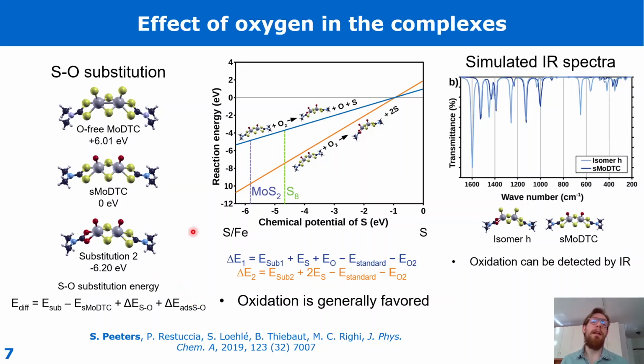To better generalize this result, we built a stability diagram in which we vary the chemical potential of the sulfur atoms, so atoms that come out as a product in the oxidation reaction. So first of all, you can see that oxidation is generally favorable because both lines are below zero for a wide range of potentials, but also that double oxidation is more favorable than the single oxidation.